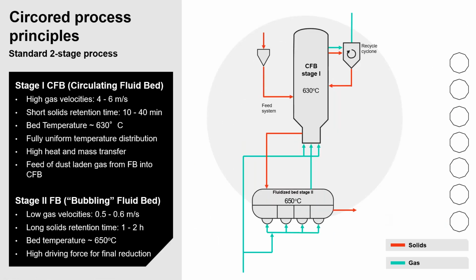Looking at the overall flow sheet, we start out with the metallurgical core of the plant, the two reactor stages. The CFB is fed with hot iron ore and receives fresh hydrogen and dust-laden gas from the FB reactor. There we have excellent mixing, which drives the reaction within 10 to 40 minutes at around 630 degrees, always depending on the nature of the ore, to the desired reduction degree.